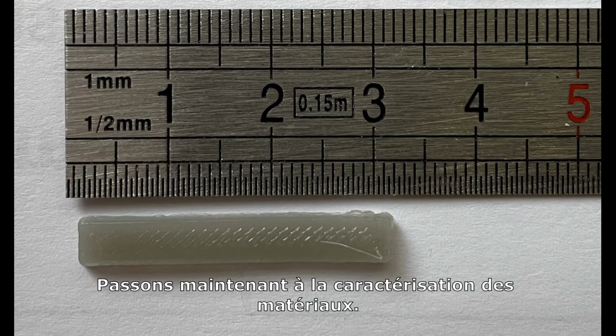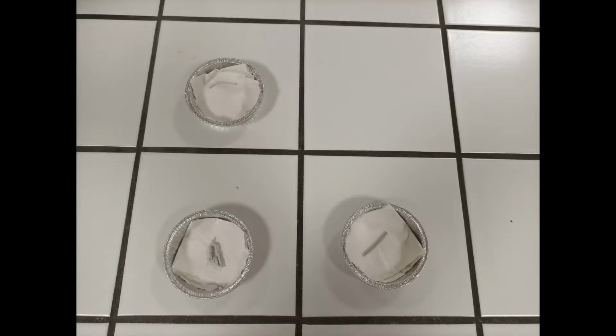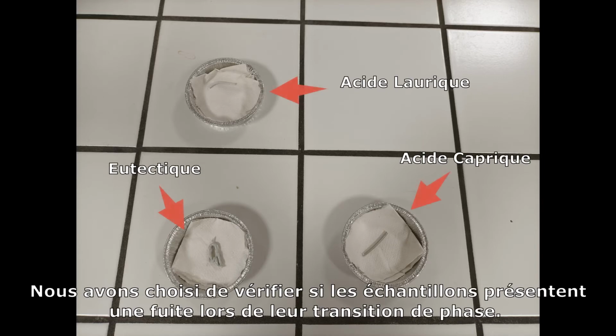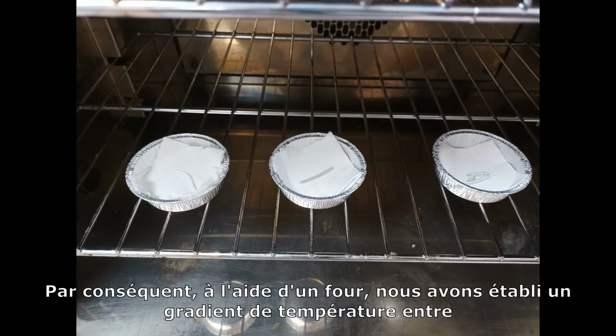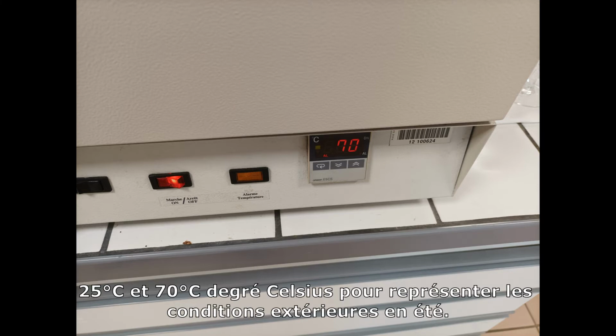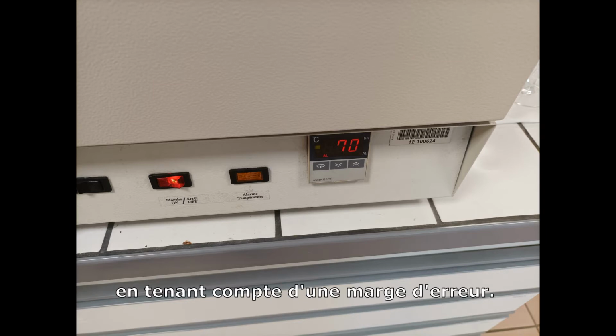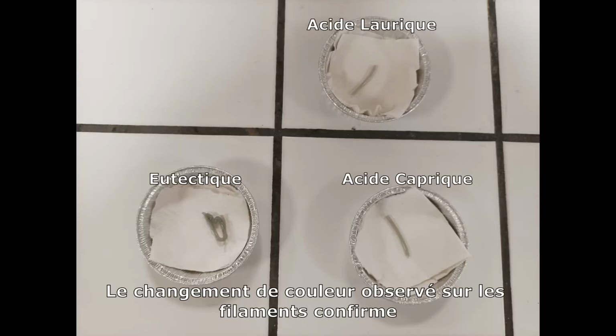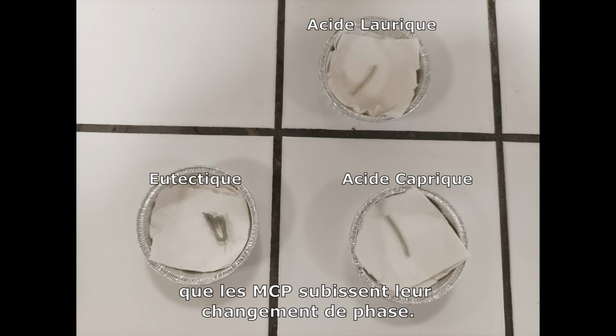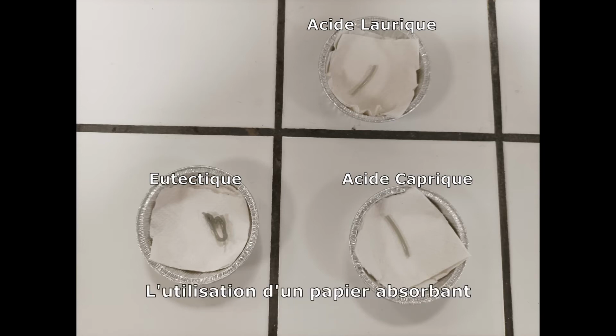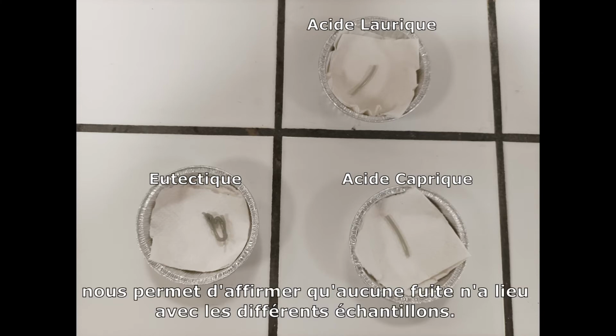Now, moving on to the characterizations of the materials. We first chose to verify if the samples were leaking when going through their phase transition. Therefore, using an oven, we established a temperature gradient between 25 and 70 degrees Celsius to represent the outdoor conditions in summer, taking into account a margin of error. The color change observed with the filament confirms that the PCMs undergo their phase change. The use of an absorbent paper allows us to affirm that no leakage takes place with the different samples.